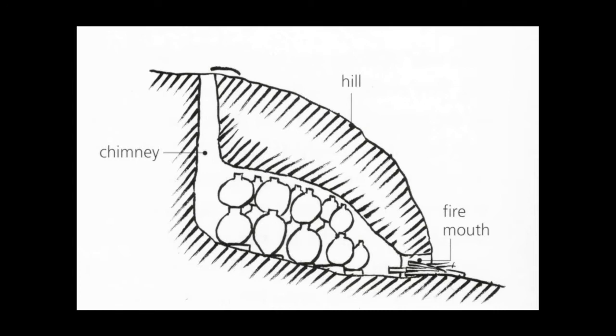Now, this is similar to what I called the Roman kiln, but it is different in that the flame is going through the ware sideways instead of coming up from underneath it. And it is predicated on having draft that's created by that chimney. That is to say, the hot gases go through the pottery, and as they are expanding, they go up out that chimney. That creates more draft to draw more air in to burn the fuel. Well, because of this, they were able to achieve much higher temperatures. We estimate that the Yayoi stuff that I showed you a minute ago was fired at somewhere between 800 and 900 degrees centigrade. This technology allowed them to achieve temperatures of 1,200 or even 1,300 degrees.